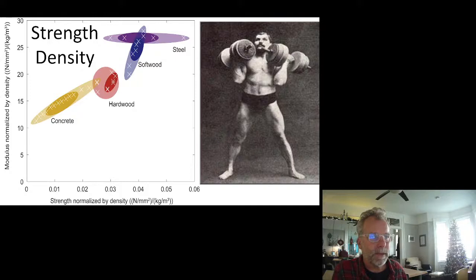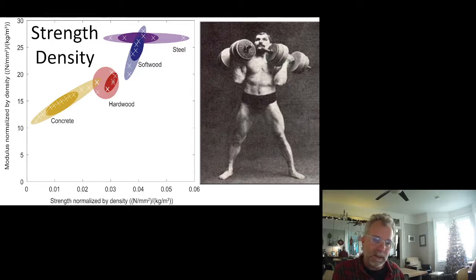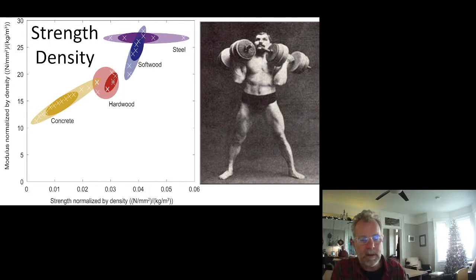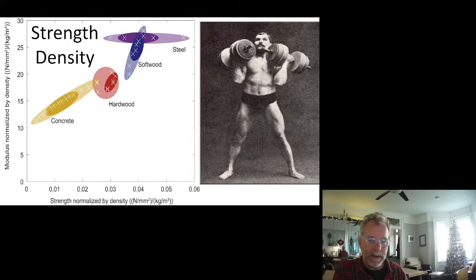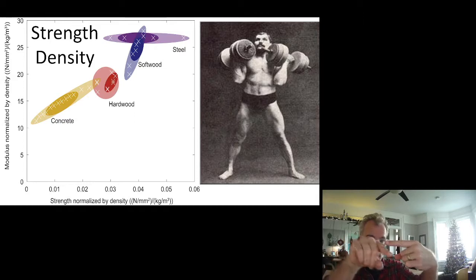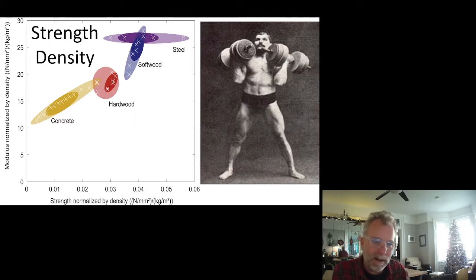Where does the weakness of wood come from? It comes from flaws in the wood. You get shrinkage checks — a long crack down a beam as it seasons. You get knots: the strength in wood is parallel to the grain, not perpendicular, so a knot causes the grain to stop and redirect, making it a weak point. As much as the knot is the hardest part to split, from a strength standpoint the knot is problematic.